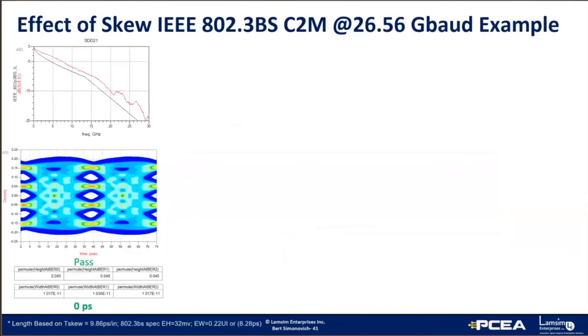And here's a more practical example of an IEEE 802.3 chip to module channel. The insertion loss shown in red meets the insertion loss mask with some margin. The minimum eye height spec is 32 millivolts, and the eye width spec is 8.28 picoseconds. And as you can see, the eye passes with margin.